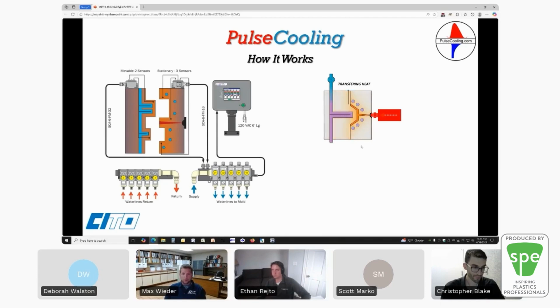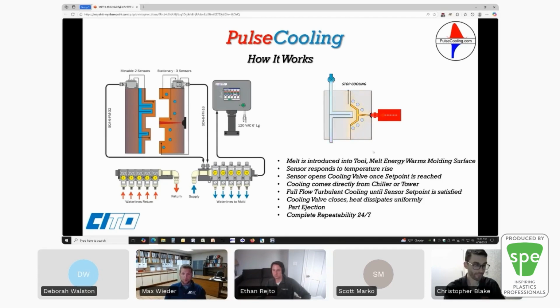The image on the right just shows a typical pulse cooling cycle, showing the melt being introduced. The energy from that melt warms the molding surface, the sensor responds to the temperature rise, and that opens the cooling valve once the set point is reached. The cooling comes directly from the chiller or tower. You have full flow turbulent cooling until the sensor set point is satisfied. The cooling valve closes, your heat dissipates uniformly, the part ejects, and you have complete repeatability 24/7.